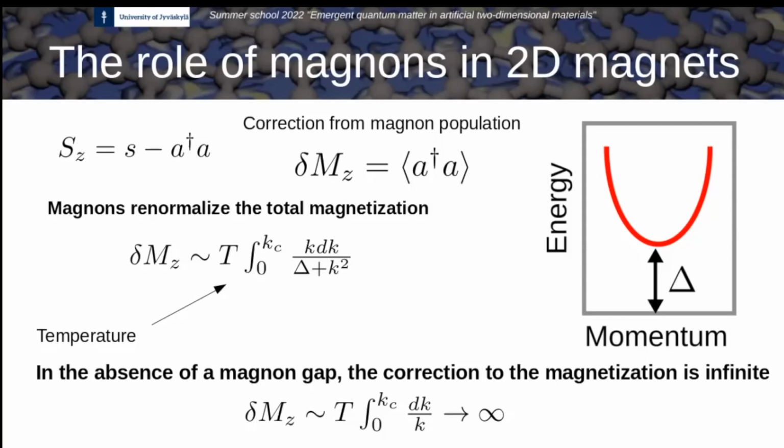So the bottom line is that this magnon gap essentially controls the critical temperature of your material. And let me emphasize that the functional form is not simple, but essentially this sets up the energy scale at which you get magnetic ordering. So in other words, magnons, and in particular the dispersion of magnons, control the critical temperature of your two-dimensional van der Waals material, and they also control how many magnons you are going to have at a certain temperature. So this statement depends on dimensionality,